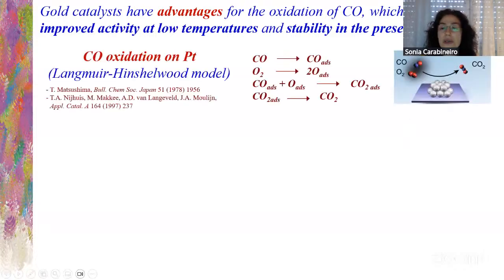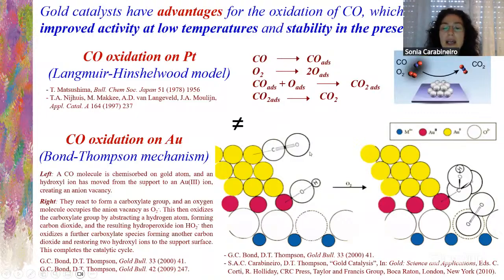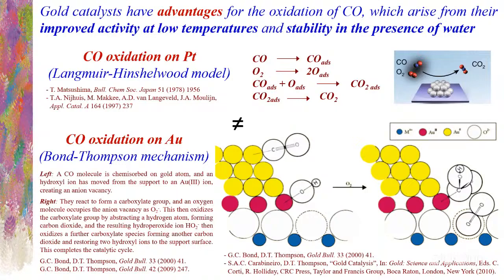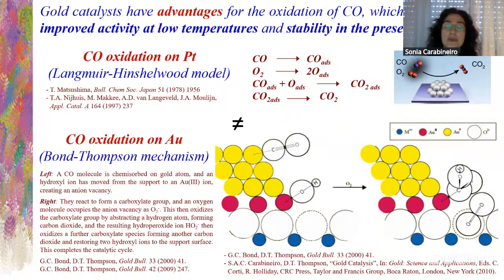As we saw, the activity is related with the reducibility of the surface oxygen. Gold catalysts have advantages for the oxidation of CO because they have improved activity at low temperatures and stability in the presence of water. The CO oxidation on platinum group metals follows the Langmuir-Hinshelwood model, which is very simple. CO adsorbs, oxygen dissociatively adsorbs, they get together and release CO2. Very easy. On gold, this doesn't happen because adsorption is not very good. So the CO oxidation takes place another way, by the so-called Mars-van Krevelen type of mechanism, which says that it is the oxygen from the support that actually oxidizes the CO. The oxygen that is being supplied is just to replenish the oxide surface.